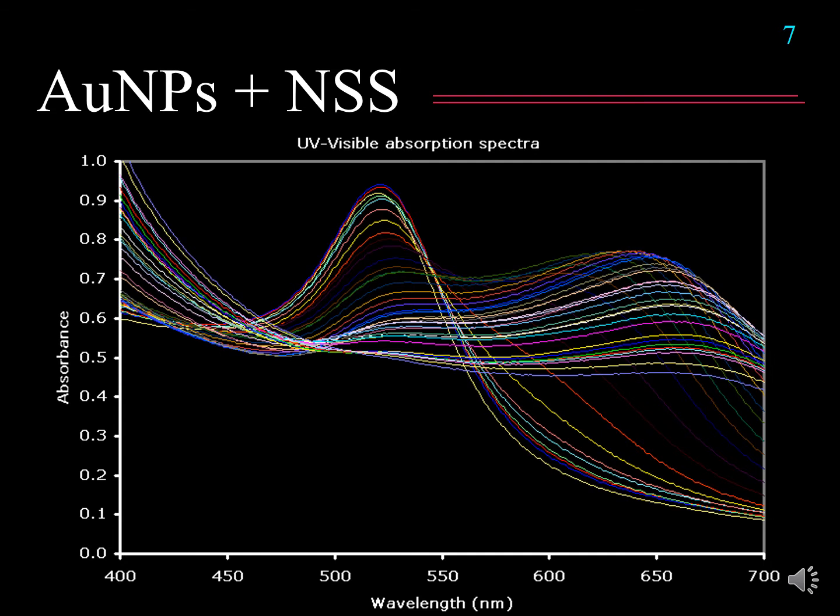So what we can see is that the surface plasmon resonance absorption band at 520 is decreasing. But then at about 600 something, the absorption is increasing. But actually this is not an absorption peak. This is the scattering peak, because the size of the particles is increasing, and after the size is big enough, they can scatter the beam of light.